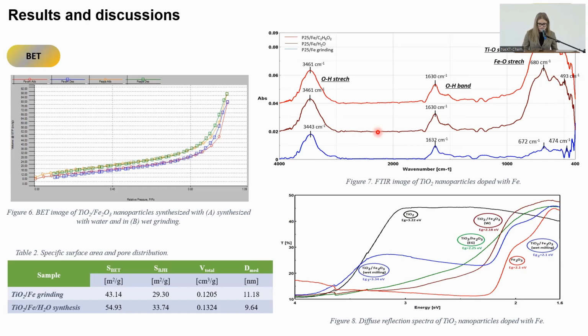It was found from the spectra that the patterns are almost identical for both synthesis samples. From the diffuse reflection spectra, it can be observed that 2 photocatalysts are visible only in the wet ground mixtures. In the case of the other mixtures, titanium dioxide practically does not exist. It confirms the fact that iron oxide is precipitated on titanium dioxide surface.